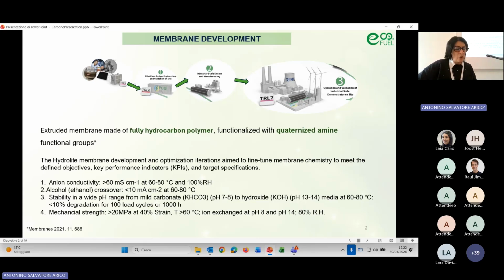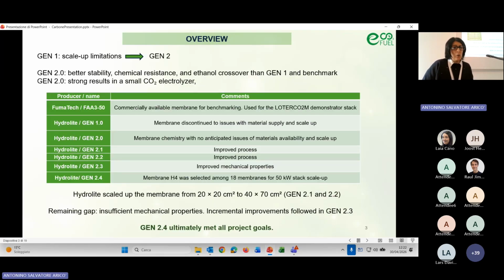were developed by Hydrolite, and should meet the key performance indicators of the project, that are a target on anion conductivity that should be higher than 60 millisiemens, in the temperature range 60 to 80 degrees, alcohol crossover lower than 10 milliampere per square centimeter, and a stability in a wide pH range, and a mechanical strength of higher than 20 megapascal.